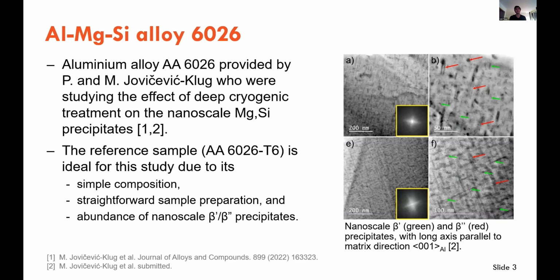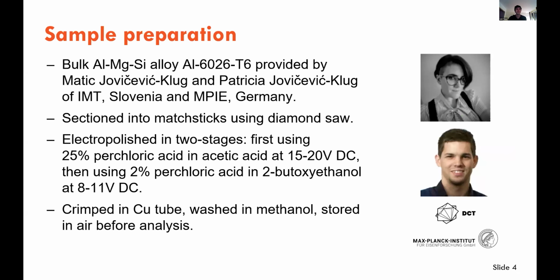Aluminium-magnesium-silicon alloys are routinely studied by atom probe. The particular alloy I was studying here was provided by some collaborators from MPIE Germany to look at the effect of deep cryogenic treatment on these nanoscale precipitates. But the reference heat treated sample is ideal for study via atom probe because it's a relatively simple material. I'll talk more about its microstructure and composition soon. But first I'll talk through the experiment which underpins this presentation. Before that, I'll talk about how the samples were prepared.